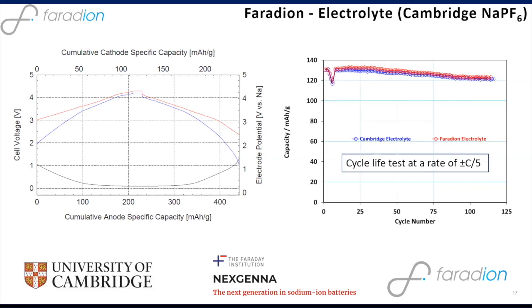We took that material at Faradion and took the NaPF6 and made that into electrolyte systems and compared it with electrolytes made with the same solvents, but with commercial NaPF6, and basically showed no difference. This right-hand side shows the testing of four cells at plus minus C/5 rate and showed no difference in performance or rate capability.